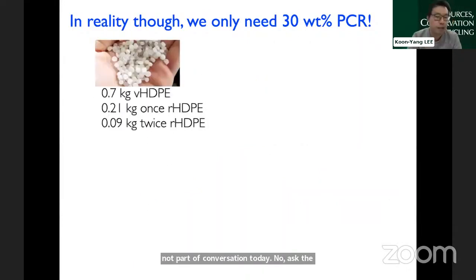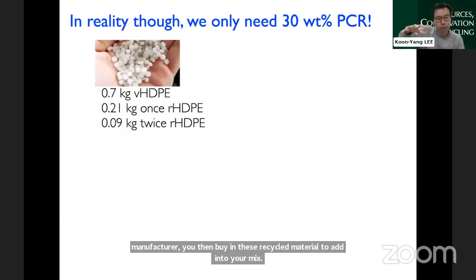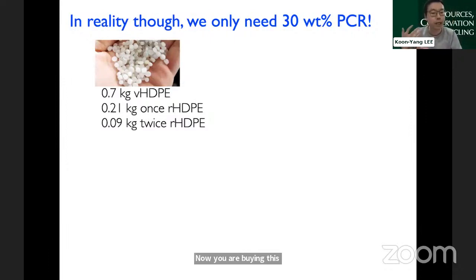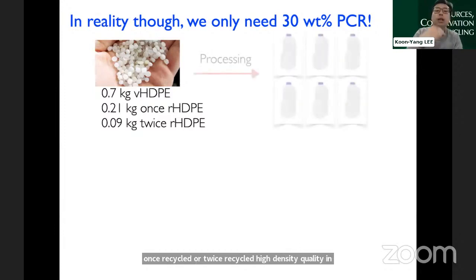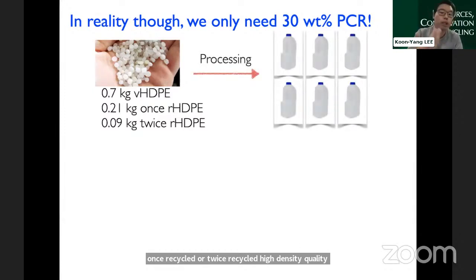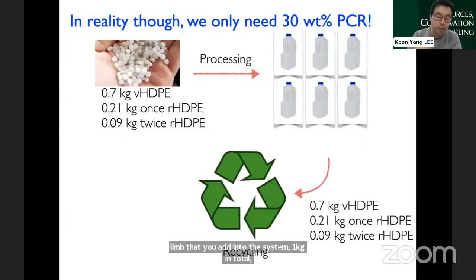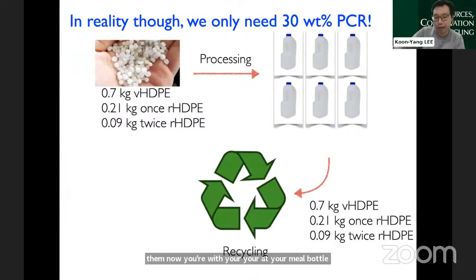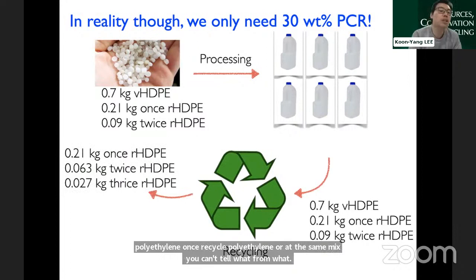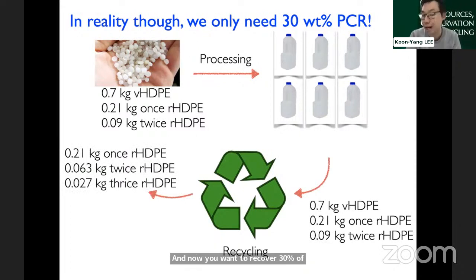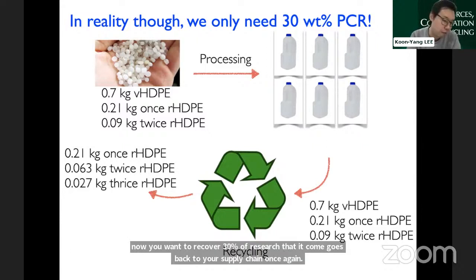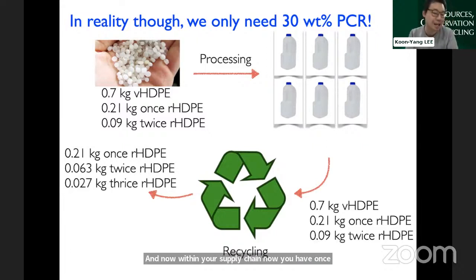Now, as the milk bottle manufacturer, you buy in this recycled material to add into your mix. This recycled material contains once recycled and twice recycled high-density polyethylene that you add into the system, 1 kilogram in total, and process into 1 kilogram of milk bottles. You then recycle them. Now your milk bottle at its end of life contains virgin polyethylene, once recycled polyethylene, and twice recycled polyethylene, all in the same mix. You can't tell what from what. And now you want to recover 30% of it such that it goes back to your supply chain once again. And now in your supply chain, you have once recycled, twice recycled, and three times recycled high-density polyethylene to be mixed with virgin polyethylene.